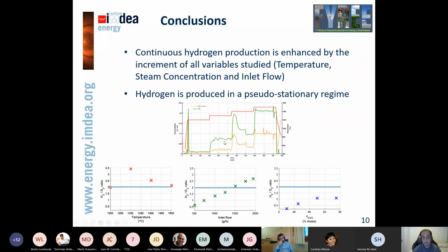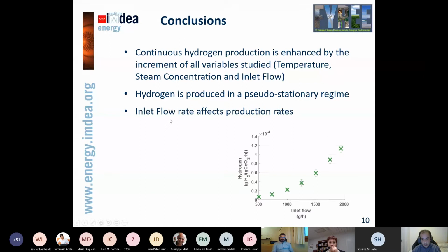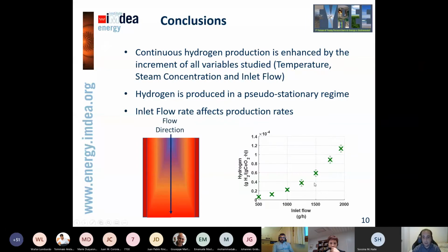So what we think is that we are somewhere close to the equilibrium, but in which oxygen and hydrogen can still be produced in a different proportion. And considering that the inlet flow rate affects the production rate, if we consider not only the diffusional issues, then it's something that can be explained. But we are also taking quite seriously into account the effect of this temperature gradient in the axial coordinate that may also be causing this continuous hydrogen production.